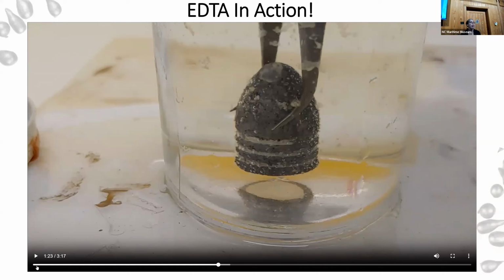But for the most part, EDTA is pretty mild, especially at the concentration we're using. We typically don't use anything higher than a 10% solution in the lab. And that's pretty true of most solutions of this type: you tend to use the lowest concentration of material that you can get away with, partially for health and safety reasons, so you're not needlessly exposing yourself to things that could potentially be dangerous in the wrong environment.